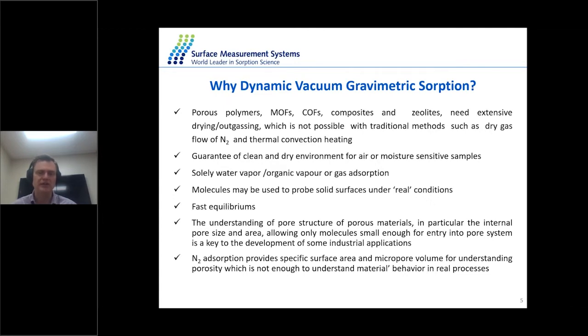Also, we probe solid surfaces with probe molecules under real conditions. This also allows us to reach fast equilibriums. In terms of catalysts, what is powerful about this system is that it allows you to understand the pore structure of the material. Most of the zeolites have well-defined cages and pore sizes. So if you select the right type of molecules, you can understand whether the size of the pores is sufficiently big for the molecules to go into the pores, or if it's too small, so the molecules are too big to get adsorbed into the pores. In that case, they're only going to be adsorbed on the outer walls of the pore structure.